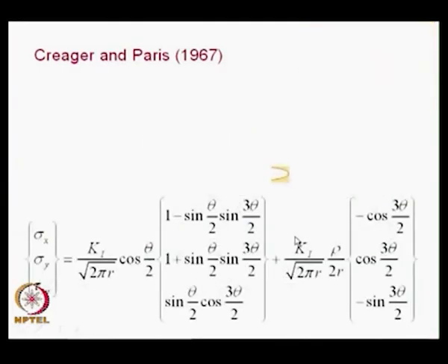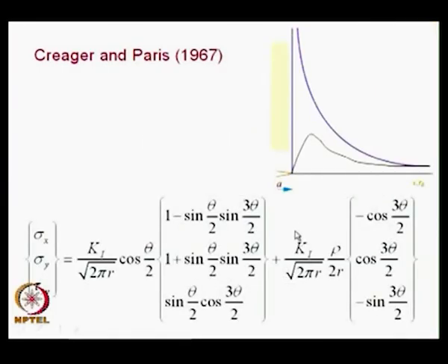And if you look at the stress field, it would be something like this. You have a blunted crack tip here, shown as sharp, but imagine that it is a blunted crack tip, and I have some variation of sigma x like this, it is 0 at the crack tip, and the sigma y and sigma x are different, and sigma x reaches a maximum value at a short distance away, and this is nothing but the Creager solution that I have shown earlier.